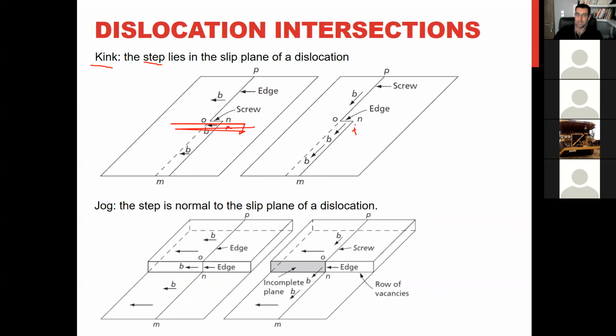Another type of step that can form is the jog. When the step is not inside of the slip plane, the slip plane of the step is different. Like this, you'll see, the slip plane was this, but this dislocation is here. It means that the slip plane is different. If you are applying a stress in this direction, this dislocation moves, and this jog also moves because the Burgers vector is inside of this slip plane, so it can move. It's not sessile.